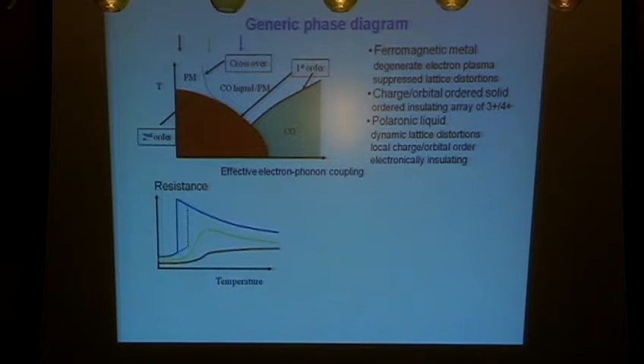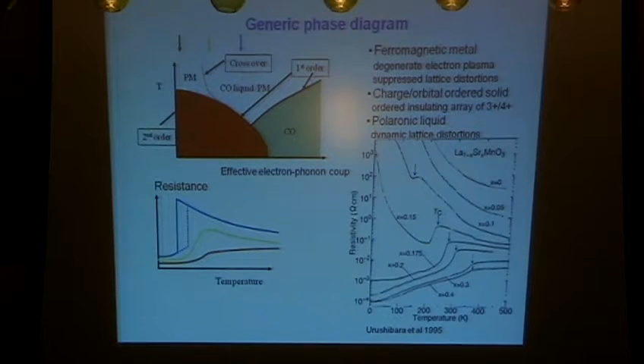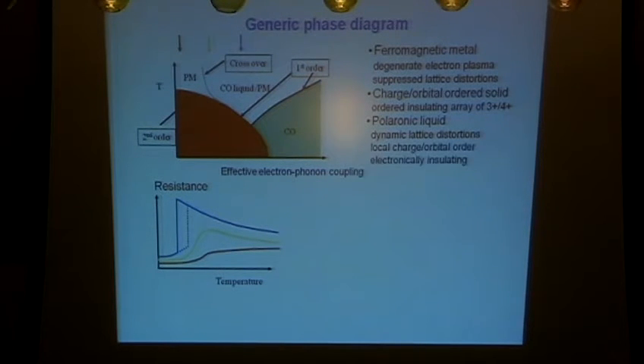And the way you see it, of course, is if you come down here with weak lattice coupling, you just see the metal behavior. If you come down here, when you're into a first order region, you will actually see a big resistive jump with some hysteresis. And somewhere in the middle, you'll see the kind of curves that I showed you before. And you know, that's, in some sense, more or less what you can already see in this data going from this regime to that one up there.